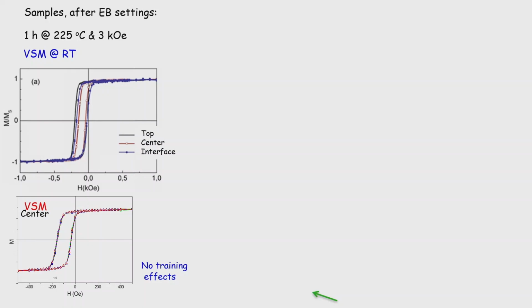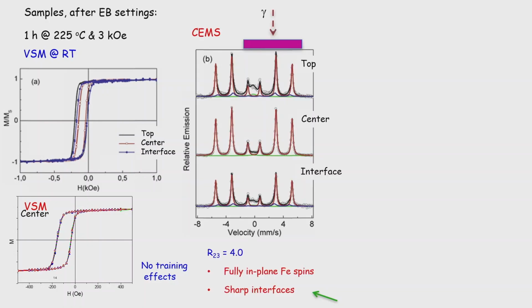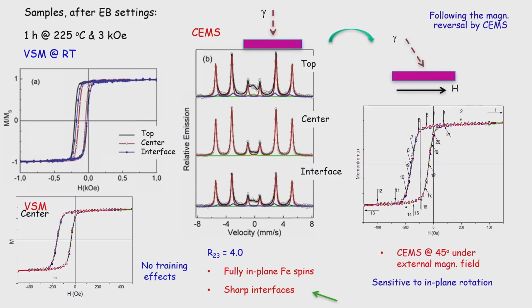from the magnetic point of view. And then by doing this more, again, we do CEMS, we see that they are fully in-plane magnetized. We see that the interface shapes are very sharp. Okay? If you have the iron 57 in the center of the sample, you see only alpha iron spectrum, for example. And then we can, let's say, go to the non-perpendicular geometry.